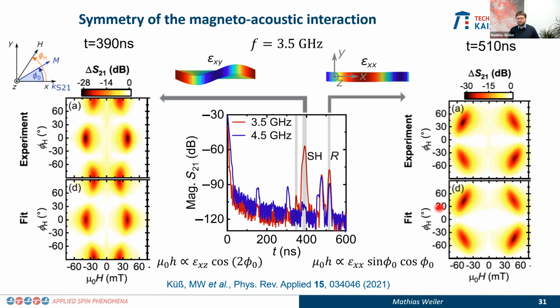Now, those people working with spin waves, they will like this. Because this allows you to operate such a device when you really want to interact with spin waves, in particular in either the Damon-Eshbach geometry, which here would be the 90 degree, or in the backward volume geometry, which here would be the 0 degree. Those are the orientations where, unfortunately, using a Rayleigh wave, there is absolutely no interaction. Okay?